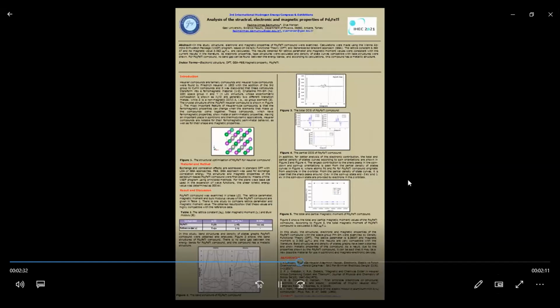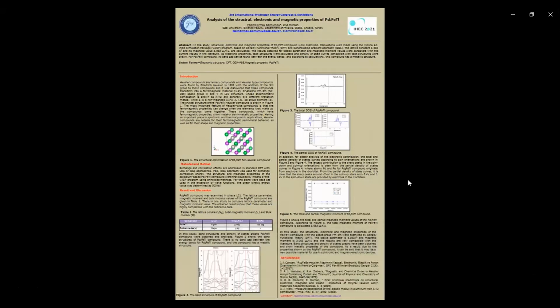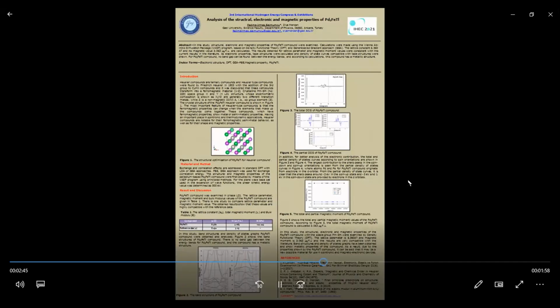There is one study to compare the lattice parameter and magnetic moment values. In the thesis written by Gaston, only the lattice constant and magnetic moment are calculated. The obtained results show that these values are highly compatible with the reference data.